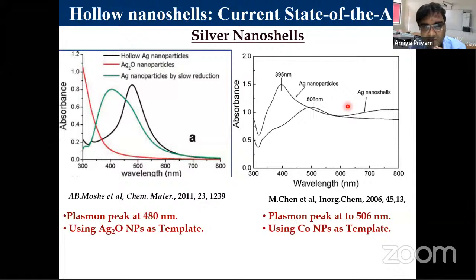So the prior state of the art when we started our work was this. Silver nanoshells. The methodology to make silver nanoshells was very primitive. There was no tunability in size to that desired range. It was only absorbing around 500 nanometers, and even in some other works we found that the peak was too broad, again not suitable for biological purposes. When you want a very precise wavelength to be used and want a very high absorption at that particular wavelength, this is again not suitable for the application that we intend to do.